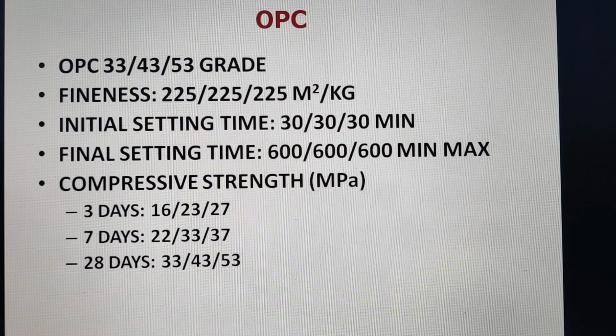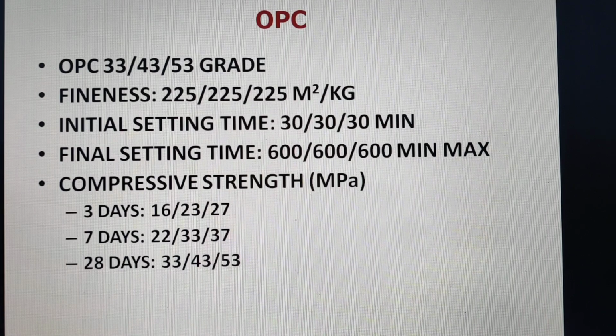These all three types of cements have the same fineness, that is 225 meter square per kg. You will see that initial setting time is also the same for all three grades of cement, that is 30 minutes, and final setting time is also the same, that is maximum 600 minutes. The only difference is in compressive strength, which is normally seen at 3 days, 7 days and 28 days.